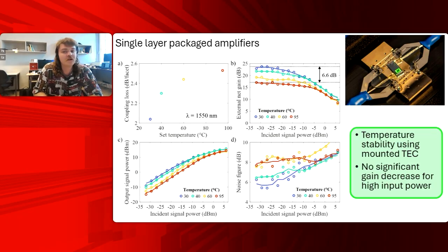Also, a huge hallmark of the platform is that it's temperature insensitive. So there's temperature stability that we've been able to measure, where instead of complete gain roll-off at 80 degrees or 95 degrees, we can see here we only lose about 6.6 dB of gain from room temperature all the way to almost 100 degrees Celsius, where the noise does go down, but at high power, there's essentially no gain decrease or no significant gain decrease for high input powers.